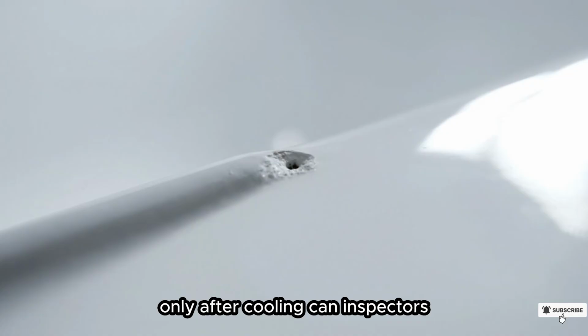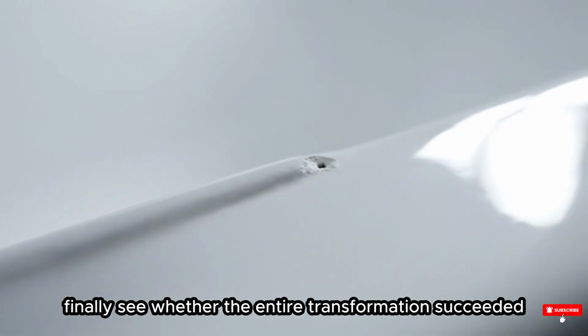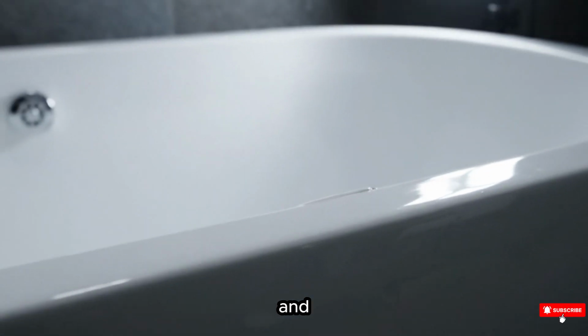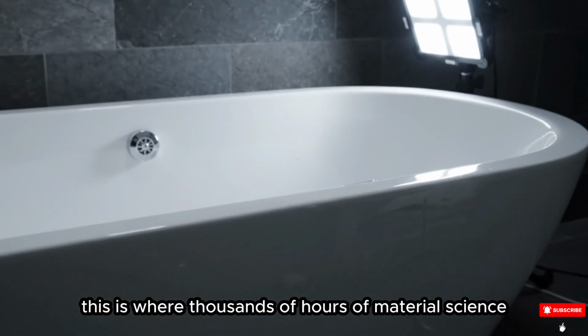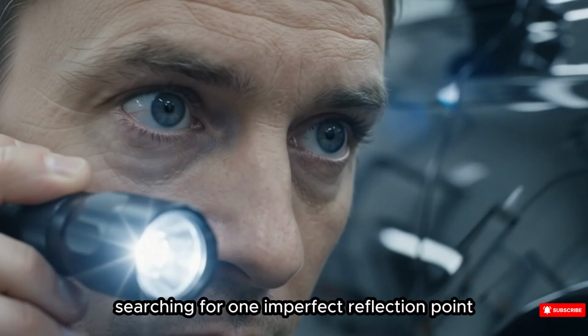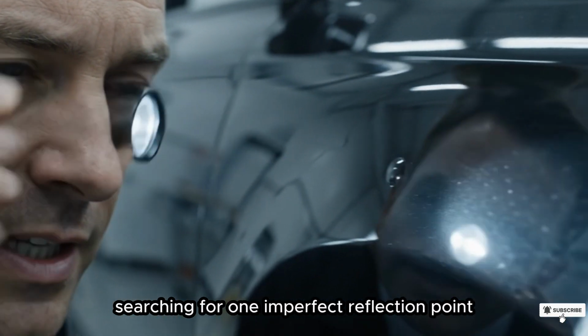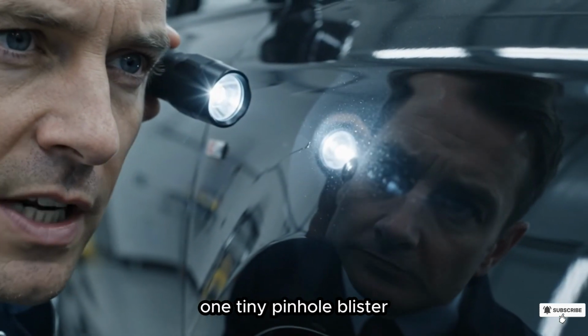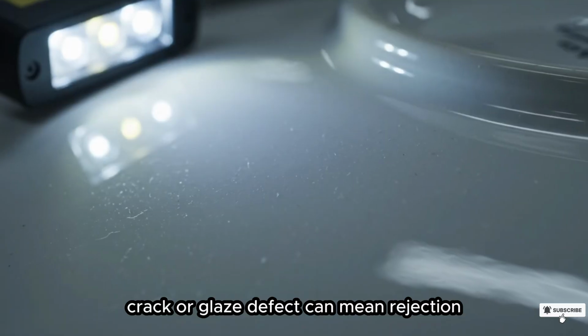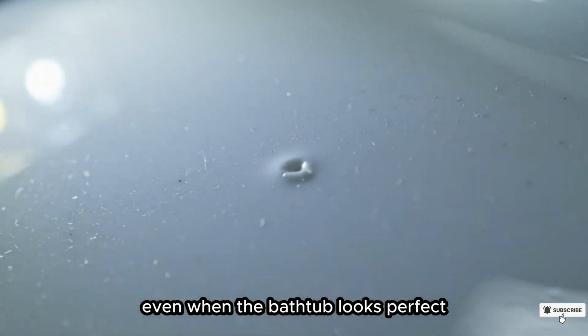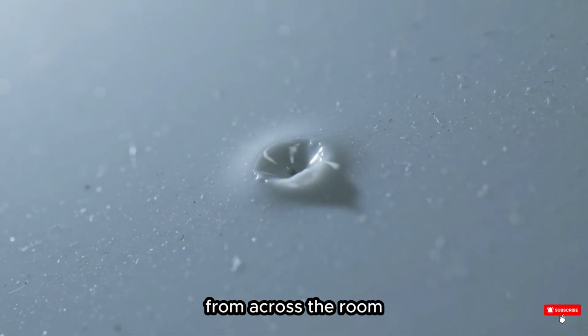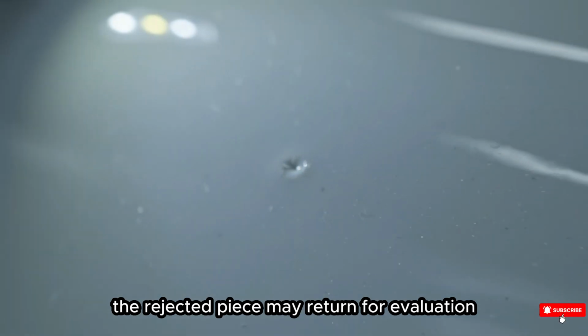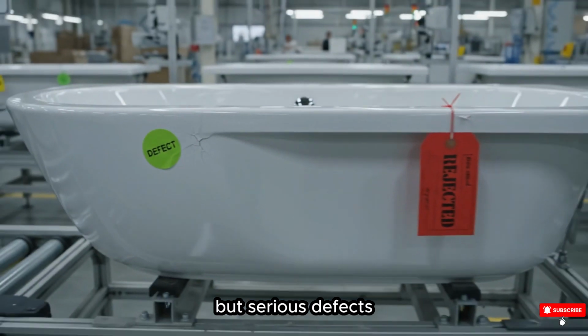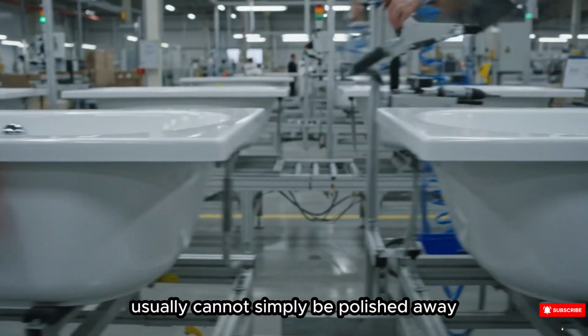Only after cooling can inspectors finally see whether the entire transformation succeeded, and this is where thousands of hours of material science meet a human eye. Searching for one imperfect reflection point, one tiny pinhole, blister, crack, or glaze defect can mean rejection, even when the bathtub looks perfect from across the room. The rejected piece may return for evaluation, but serious defects usually cannot simply be polished away.